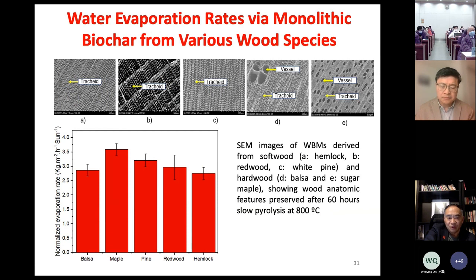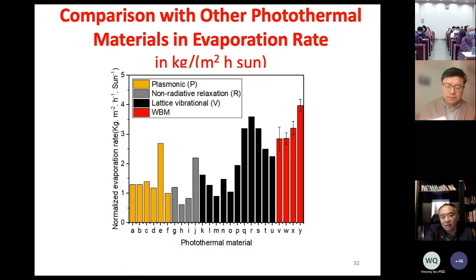Okay. So here are some results of evaporation rate of water from different wood biochar. What you can see here is that we tested maple, pine, redwood, and hemlock, and we found that maple actually had the highest evaporation rate. Okay, and this is a comparison in terms of evaporation rate with published data.